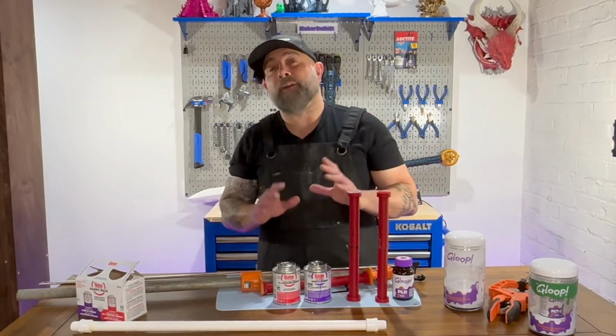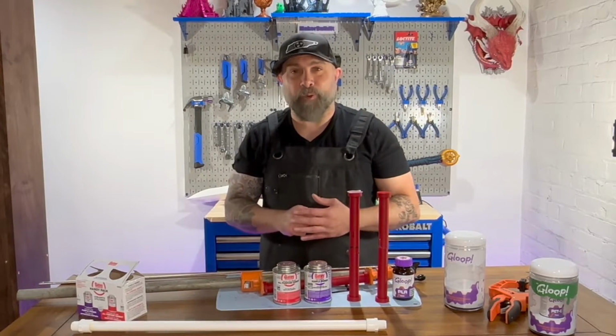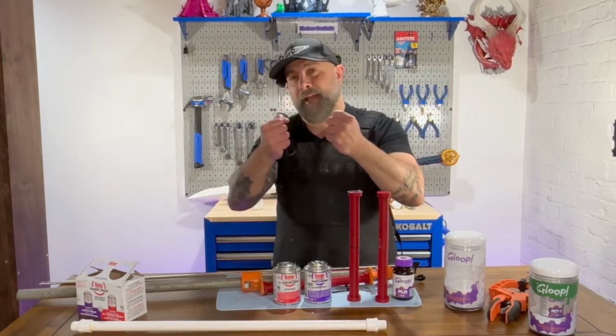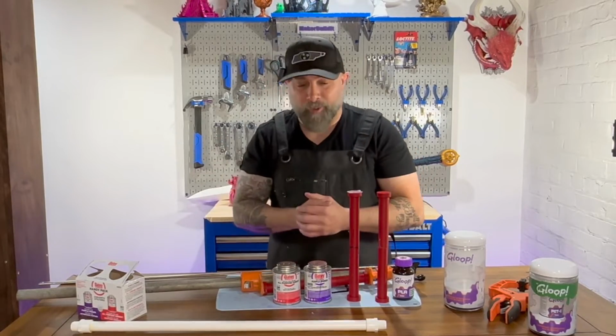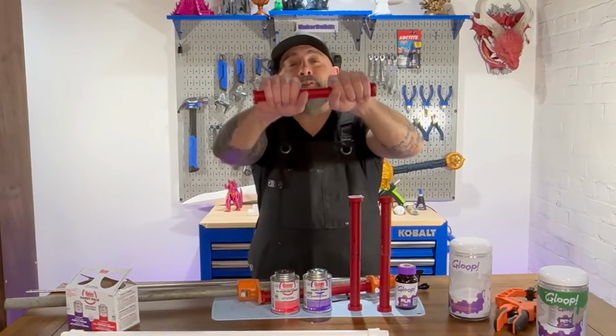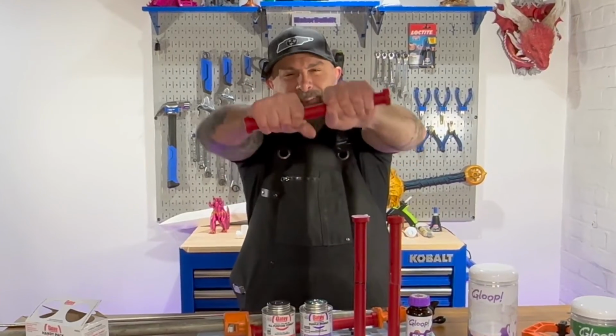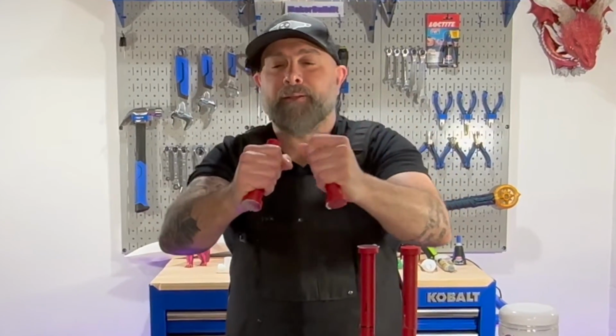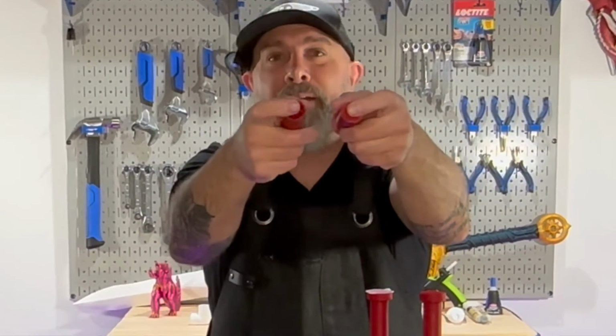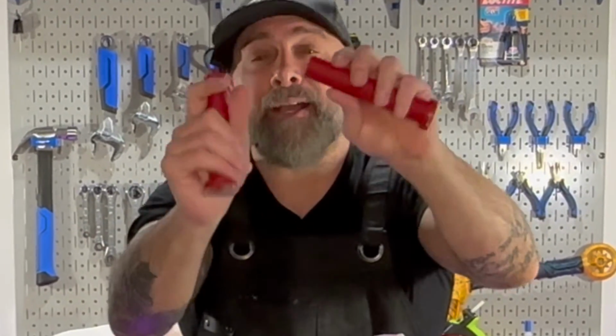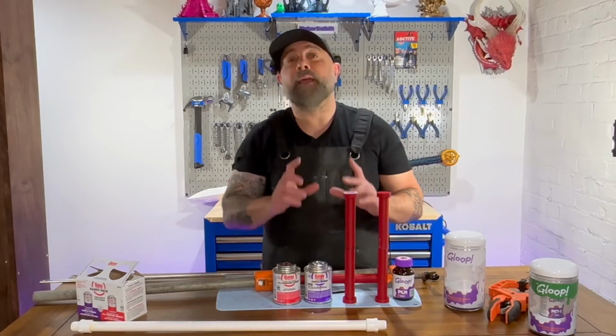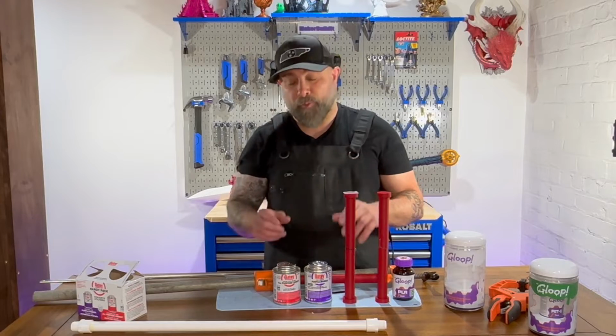So we let these dry for a little over 24 hours. Now let's see if we can actually snap the bond apart. This is our 3D printed glue. We're going to do that one first. Okay, it actually broke the PLA. The bond actually held.